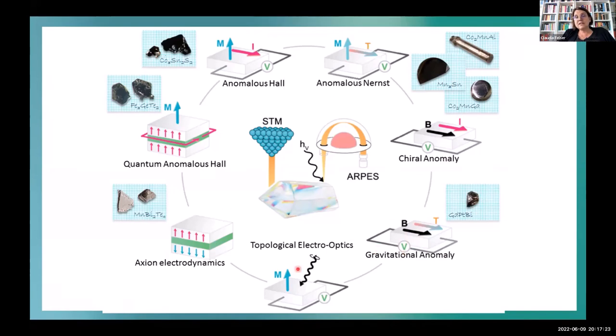Anyways, this is only a part of what you can see in transport. And for sure, people like to do angle-resolved photoemission to see simply the electronic structure and the surface states of this material, and STM, scanning tunneling microscopy, also. So you have a slew of methods which you can already apply if you have a simple lab. If you have a PPMS in your lab, and I think everywhere has a PPMS nowadays, there are already so many crystals around which have all these interesting, or partially these interesting, properties. Honestly, not every interesting property is yet proven in these crystals. So simply take one crystal, for example cobalt manganese gallium, or maybe even the cobalt three tin two sulfide. Nobody has yet measured the gravitational anomaly, and I'm sure it's there.